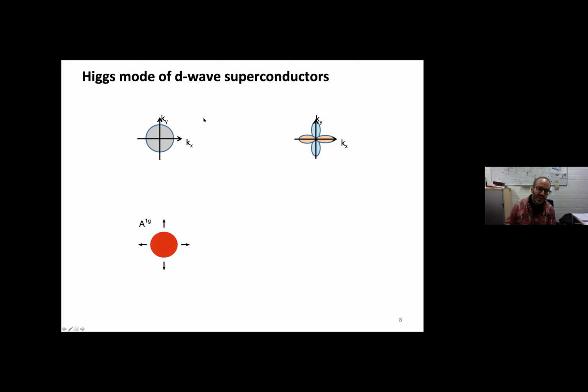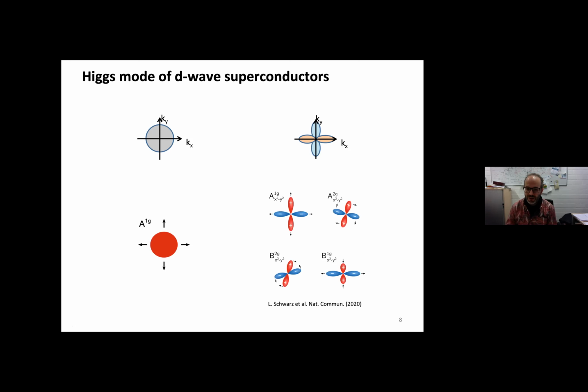For the S-wave superconductors, in principle, the only possibility for oscillations are fully symmetric oscillations in the system, which we could say, in a phonon sense, we could label them with an A1G type of oscillations. However, we could show that in these D-wave superconductors, depending on your momentum transfer of the system, you could do different symmetry quenches to this system, and in principle that would allow you to access different kinds of oscillations, like a fully symmetric one, but also an antisymmetric one. So this would be like a center of mass and the relative motion of the system, but depending on the quench of your system, you could also set a rotation oscillation or a clapping oscillation of these superconducting lobes.